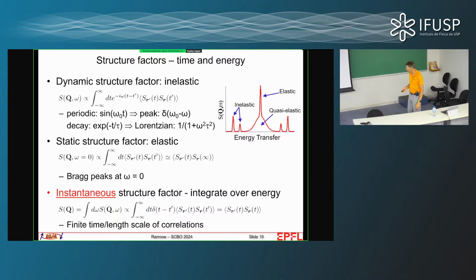I can also, however, integrate over all frequencies, and then what happens is that the integral over frequency becomes a delta function in the two times in the problem. And so that means that the energy integrated structure factor, or the instantaneous structure factor, becomes equal to the equal time correlation function. So even if I do not have static correlations in my system, they are allowed to fluctuate in time. But what neutron scattering does is it takes a series of snapshots and analyzes each of these pictures and sees how much correlation there is, and then it takes the average of all of these correlations. So even if things are fluctuating, we can still tell whether on average neighboring spins, for instance, are somewhat correlated or not.